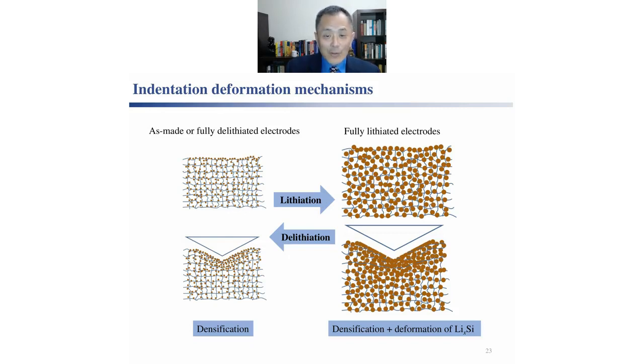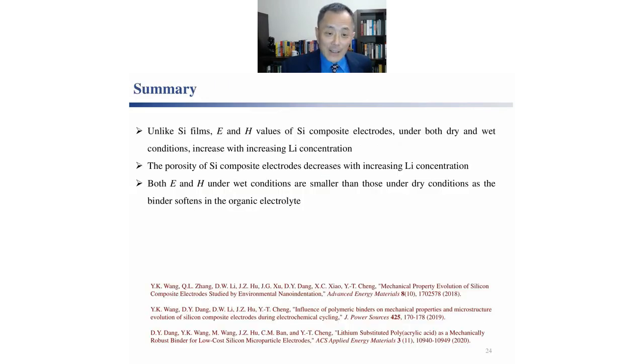When the porosity is low, when silicon is filled with lithium, the particle size increases, porosity decreases, and deformation is caused by both the polymer deformation as well as the deformation of the silicon lithium alloy particles. Although the modulus of each individual particle decreased, because of volume change, the solid fraction increased upon lithiation, so the overall modulus and hardness increases with lithiation. And that is our measurement of the silicon composite electrode.